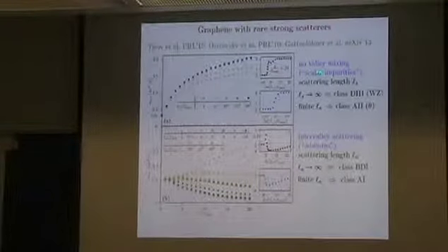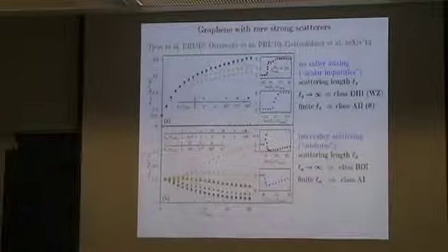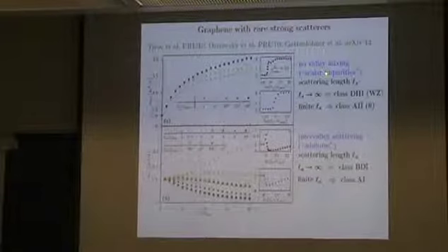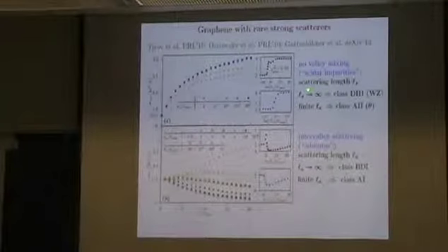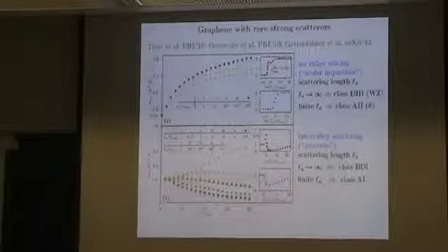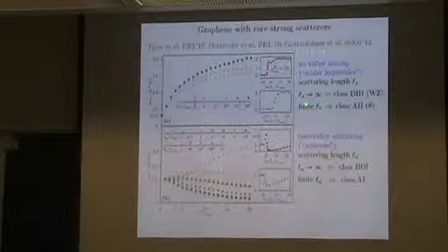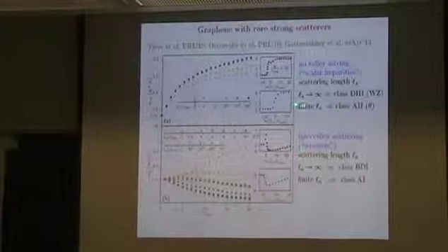And so now there are two different types of scatterers. The first we call scalar impurities, which do not mix valleys. They are short range, short compared to the distance between them, however sufficiently long range, so finite range, such that you can neglect intervalley scattering. So by hand we put in a scattering matrix that doesn't mix valleys. And another type we call adatoms, these are really sharp and they do mix valleys. In each case, the strength of the scatterer is characterized by the scattering length, which we call LS for scalar and LA for adatoms.